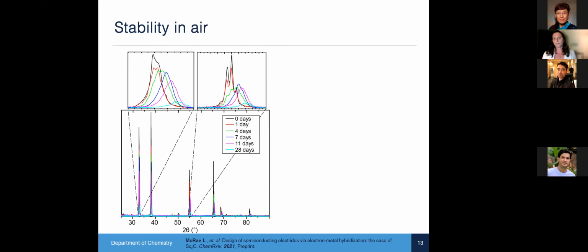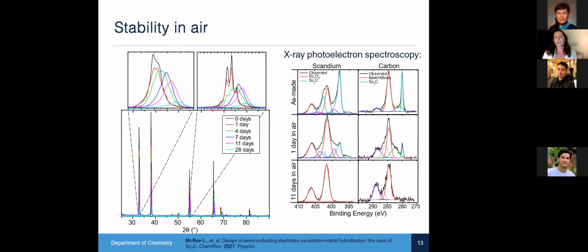So we wanted to explore the mechanism of oxidation. We used X-ray photoelectron spectroscopy to understand oxidation on the surface of the material. You can see before any oxidation occurs, we have very nice peaks for both scandium and carbon, indicating that we have scandium carbide present, and then some amount of scandium oxide or adventitious carbon. After 1 day in air, we have a decrease in the intensity for the scandium carbide peaks compared to the scandium oxide and adventitious carbon peaks. And by the 11-day time point, we see no evidence of any scandium carbide left on the surface.